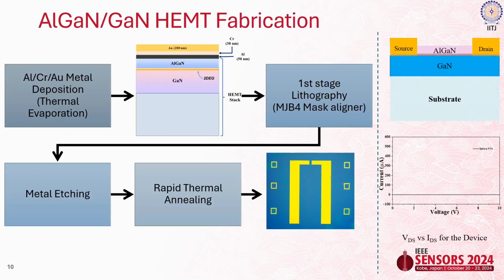So how did we fabricate this sensor? We started first with the epitaxy growth of these structures. After that, we started with the metal deposition over the wafer. On top of this AlGaN-GaN interface where 2D electron gas is already formed, we are depositing aluminum, chromium, gold over it, and then using a mask aligner and lithography, we are patterning. Once the pattern is done and this sensor is made, we are doing rapid thermal annealing.